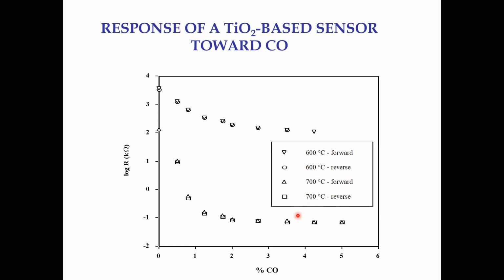That means you are getting practically completely reversible, completely recoverable sensor, which is expected. Because remember, your target gas is interacting with the surface adsorbed oxygen. It's not changing the oxide. It should be, in principle, completely recoverable.